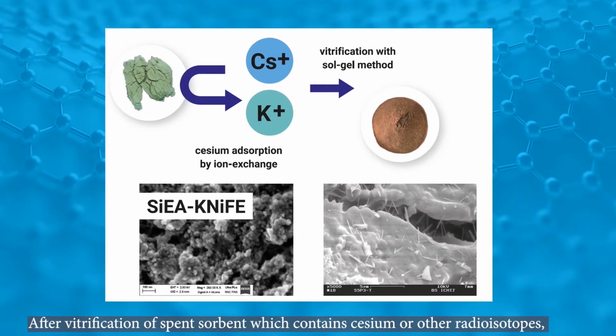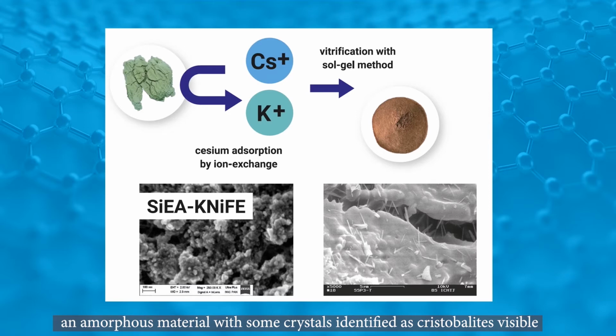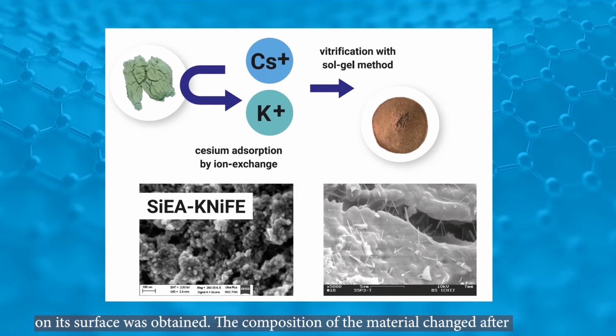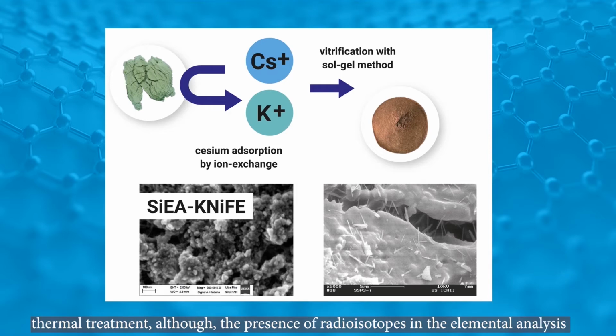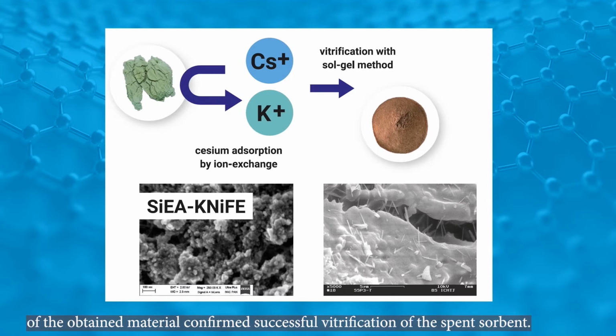After vitrification of spent sorbent, which contains cesium or other radioisotopes, an amorphous material with some crystals identified as cristobalites visible on its surface was obtained. The composition of the material changed after thermal treatment, although the presence of radioisotopes in the elemental analysis of the obtained material confirms successful vitrification of the spent sorbent.